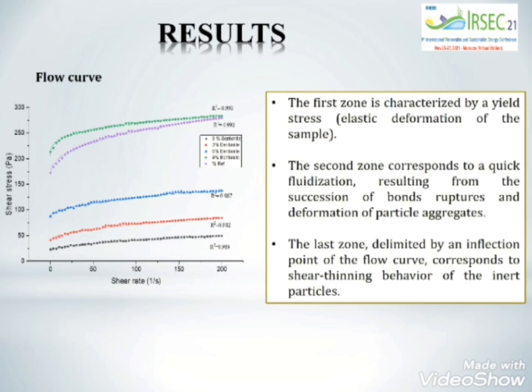The first zone is characterized by a yield stress, which corresponds to an elastic deformation of the sample, and then the second zone corresponds to a quick fluidization resulting from the succession of bond ruptures and deformation of particle aggregates. The last zone, delimited by an inflection point of the flow curve, corresponds to shear thinning behavior of the inert particles.